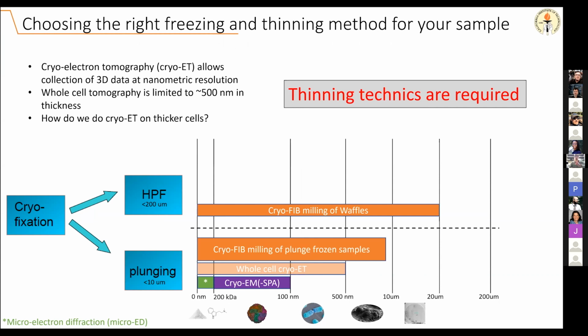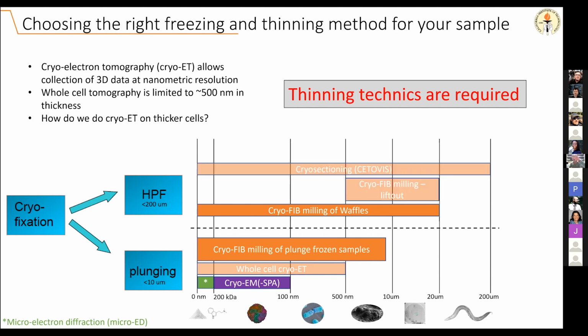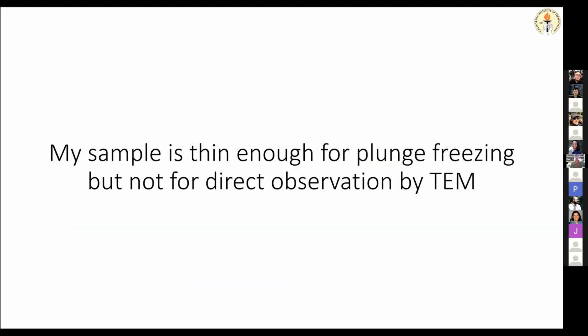And so we're going to be talking about two thinning methods that require cryo-focused ion beam. We're going to talk about cryo-focused ion beam on plunge frozen samples, and also this new variant called the waffle method. And I'll also just very rapidly talk about two others, because I think it's good that you also know that there are more exotic ways of thinning samples that are even thicker. And so basically, cryo-FIB milling can be performed on plunge frozen samples up to 10 microns, which is the limit of what can be vitrified at ambient pressure. And then anything that's above 10 microns will need to high pressure freeze it.